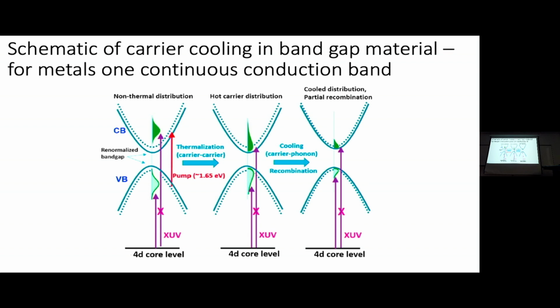And so what we do is with the laser pulse, we create hot holes and hot electrons. Initially, they're not Fermi-Dirac. So the first thing that has to happen is they have to thermalize to become more like a Fermi-Dirac distribution. They should obey Boltzmann statistics, essentially, and they will on a very short time scale. And then, eventually, that should communicate with the lattice and cool down, and eventually we should get back to room temperature. Okay? So this is pictorially what's happening here, and we're probing it through, say, the 4D core level of the tellurium.